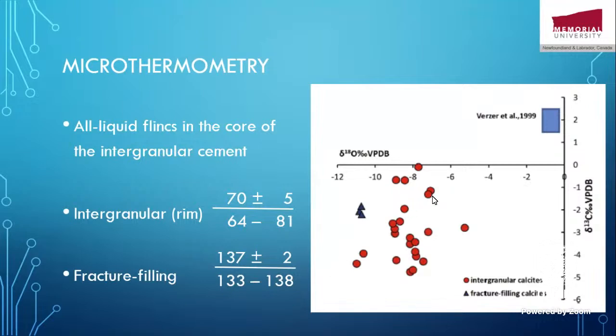While calculating from the melting point, let's look better at the delta carbon 13 and delta oxygen 18 of those cements. You will find that the fracture cements were not very common. They were rare, and the intergranular cements have delta oxygen 18 and delta carbon 13 very close. They are a bit marginal, on the enriched side of the delta O18, but the fracture cement is on the depleted side because of the high homogenization temperature, of course. But if you look at the delta carbon 13, they are overlapping, so there is no difference in the delta carbon 13.